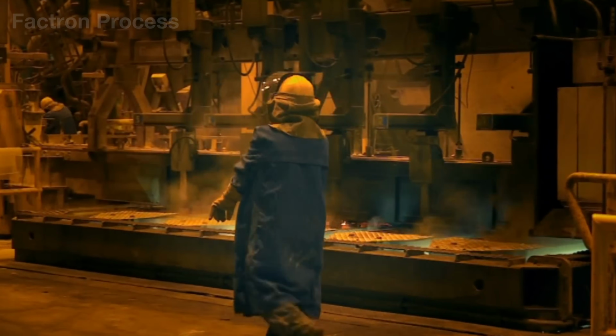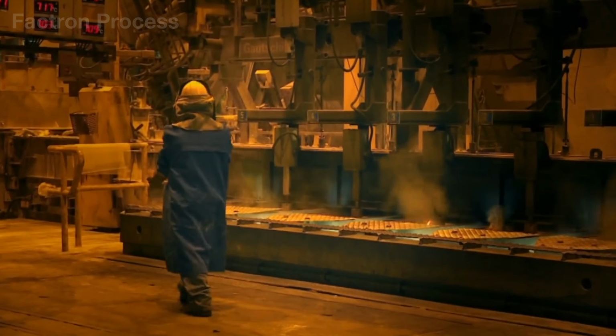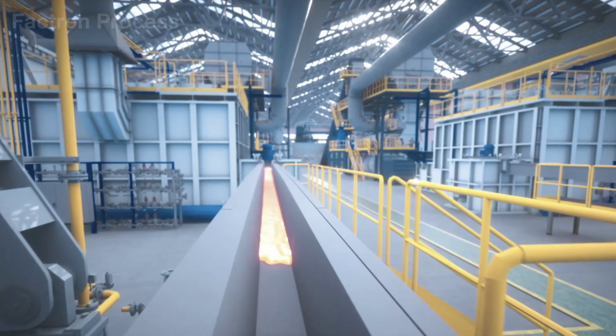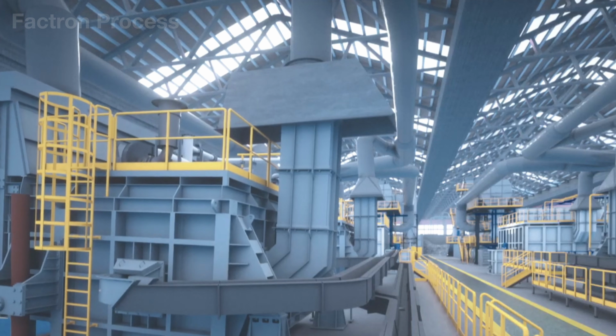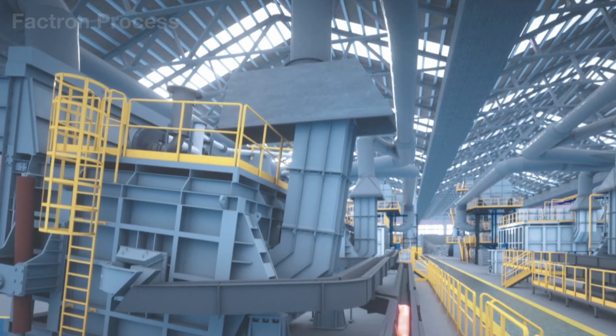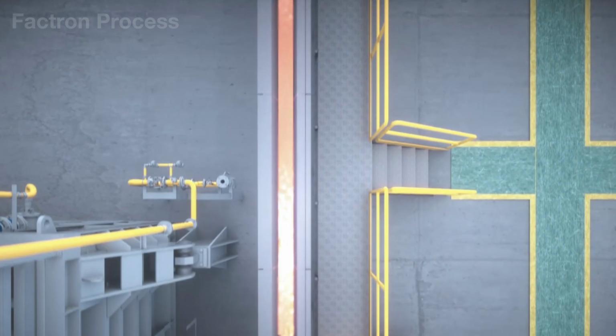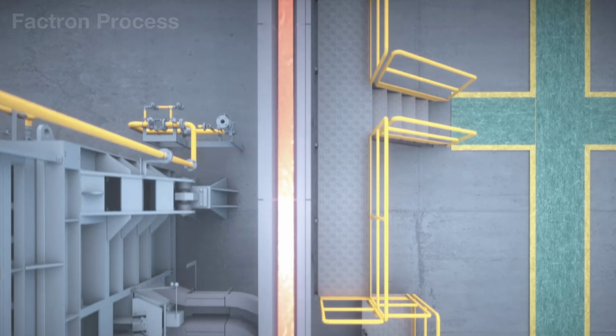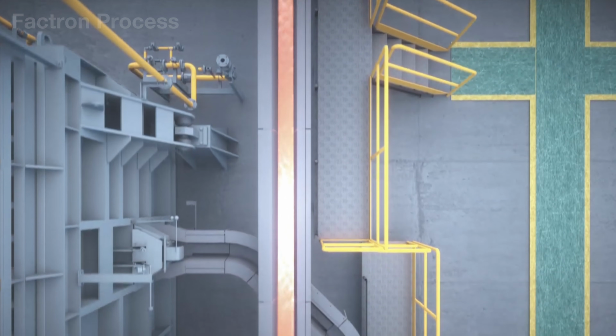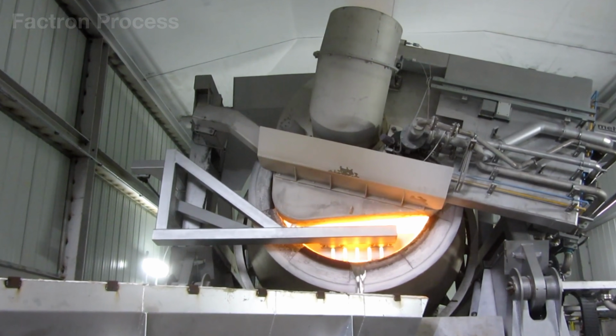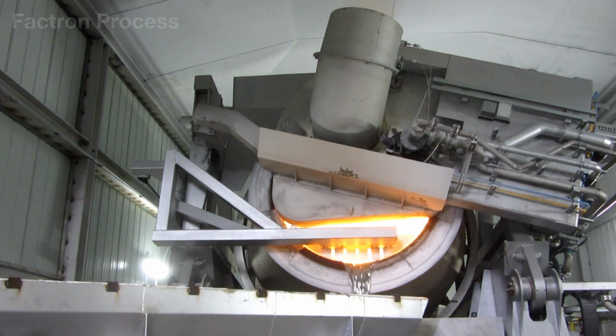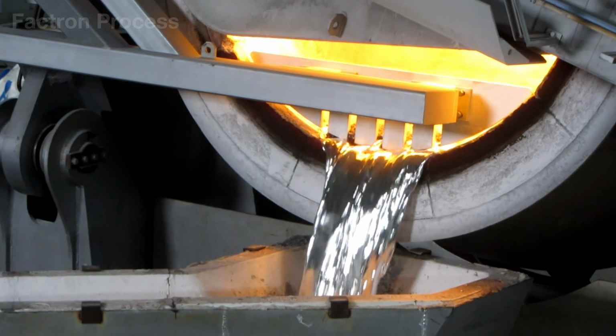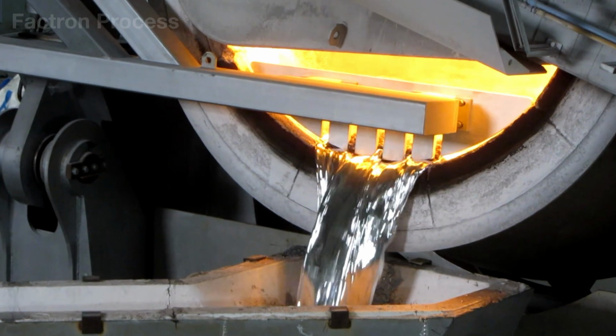The pouring rate, descent speed, and cooling water flow must be closely synchronized, so the metal solidifies evenly from the outside inward. If cooling becomes uneven, the slab may develop porosity, hot cracks, or internal stresses that could cause problems during rolling. Sensors therefore continuously monitor the metal level, temperature, and casting speed throughout the process.